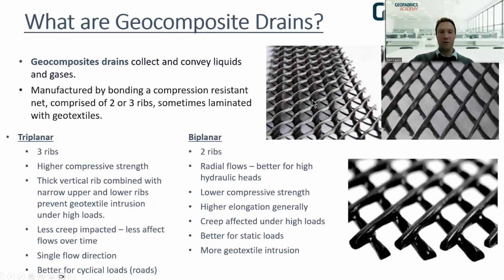So if you wanted to put this under a road, you would probably be using a triplanar net. Biplanar nets, 2 ribs, as I said, they allow for radial flow, so better probably for higher hydraulic heads, maybe water storages. Lower compressive strength though, higher elongation generally, easily affected by creep under high loads, probably better for static loads, and you will get more geotextile intrusion due to the makeup of the material. You can imagine if you've got a geotextile over the top of this triplanar, you won't get as much pushing into that flow path.